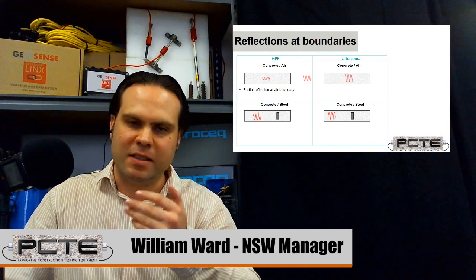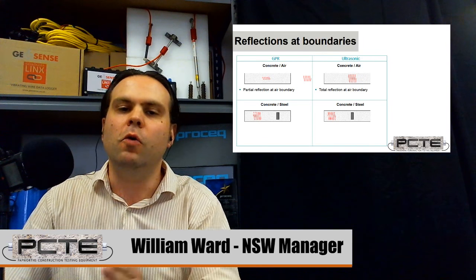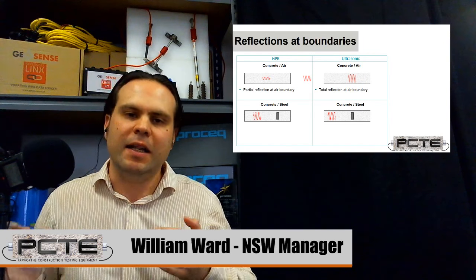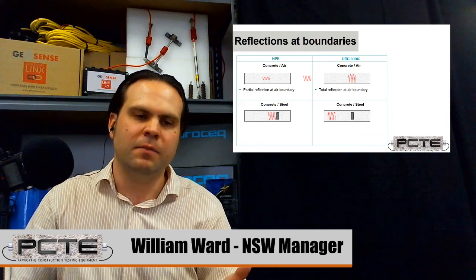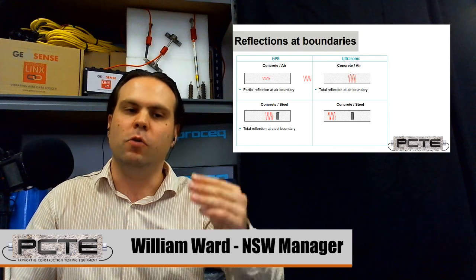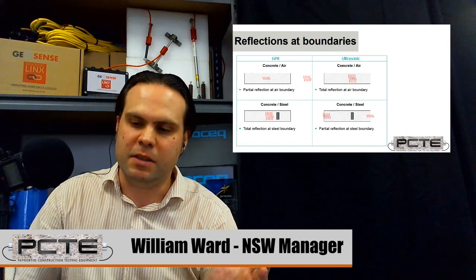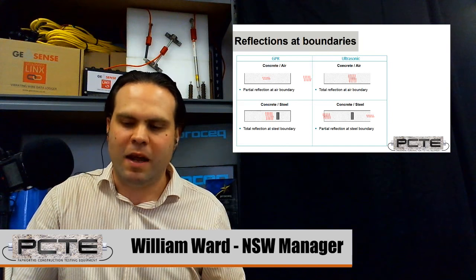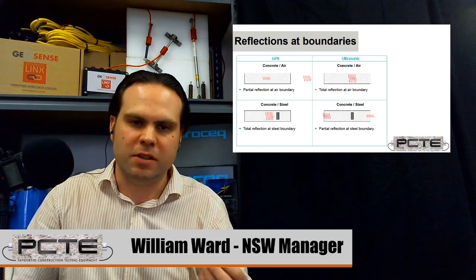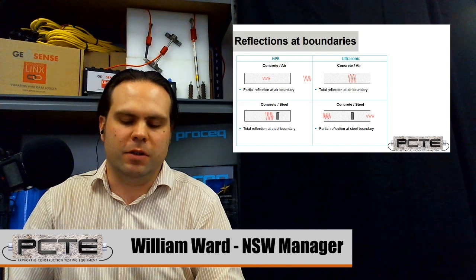So if we use a sound wave to a concrete air interface, we return all of the energy. So we get a really clear image of that break, but we can't see beneath it. Similarly, if we send a radar signal to a steel embedment or a steel plate, it's completely reflected. All the energy comes back to our sensor. And if we send a sound wave to a steel interface, some of the energy will travel through. We don't have as strong an ability to image the steel or see the steel, but we can see beyond it.